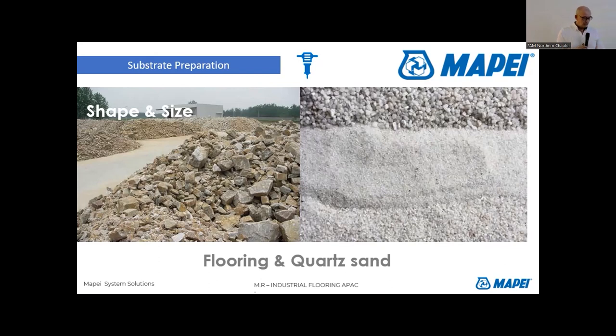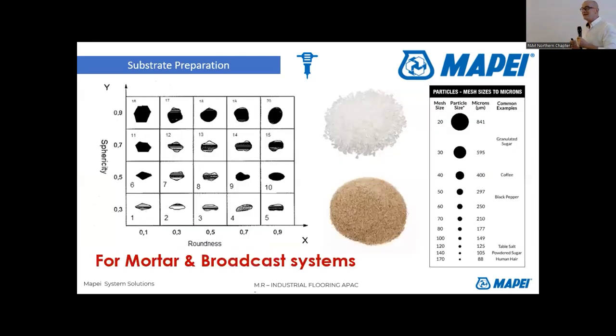So now here is one thing I want to make you understand. Here is a sample. One looks very dense, one looks very rough. If an applicator uses, say, one sand size and mixes a little bit, 10 kilo sand with 1 kilo resin, then you mix it, put it on the floor. The question is the size of the aggregates. If he does that, he gets maybe 25 newton per square millimeter, maybe more or less. So we sell our own sand where we have a combination. The combination is the combination of size and shape. You need the grading, you need the shape, a round shape in order to get an interlocking.